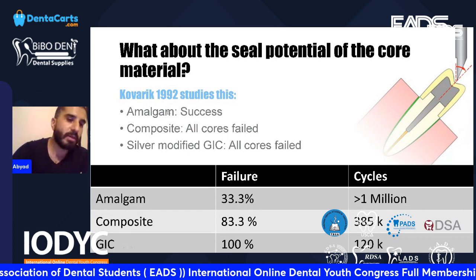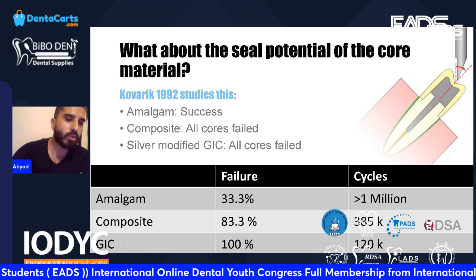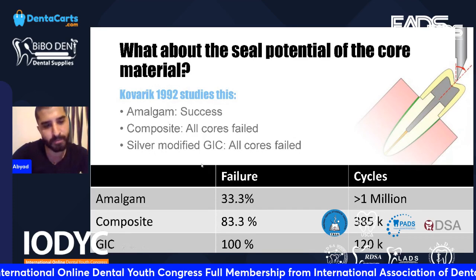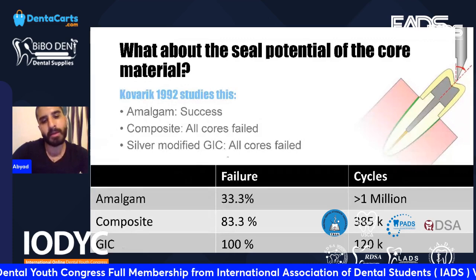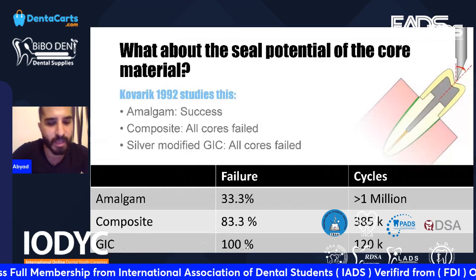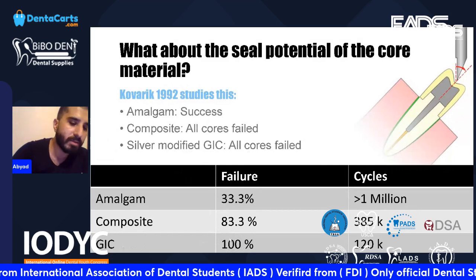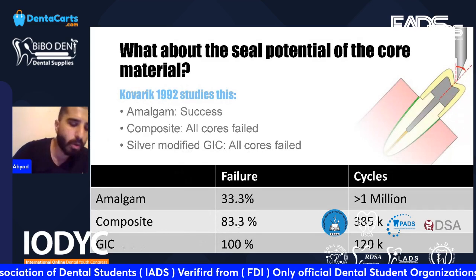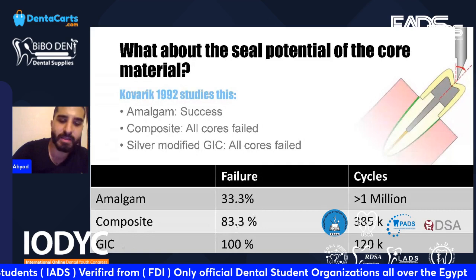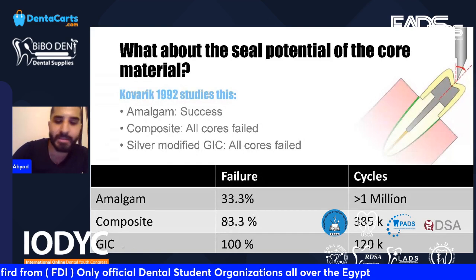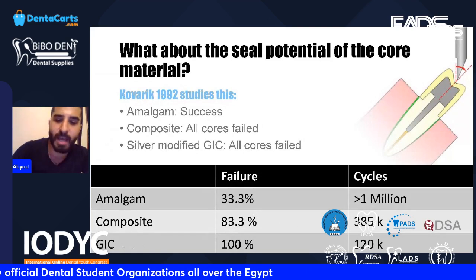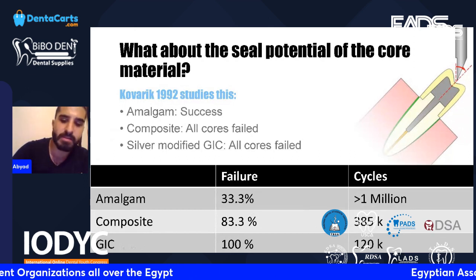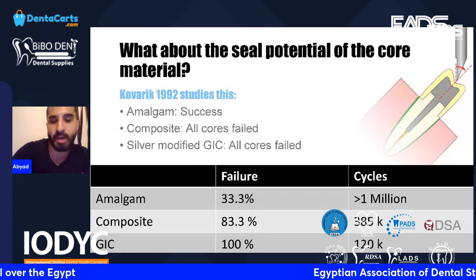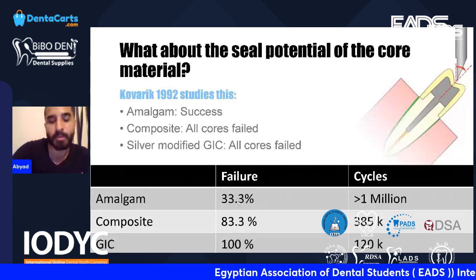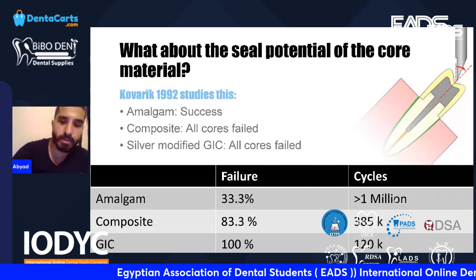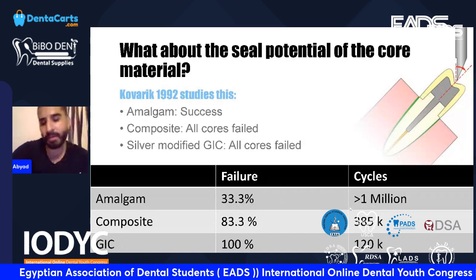So in his study, he had amalgam core, composite core, and silver modified GIC, glass ionomer cement. The glass ionomer cement almost always failed, and that's why I don't recommend it being used as a core material at all. The composite failed, more than 80% of the samples failed after 385,000 cycles, and the amalgam survived with a percentage of 70%, which is really good, after 1 million cycles.